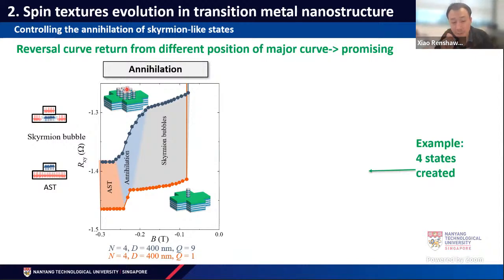small nanodots. However, when we did the measurements, we realized that the electrical measurement is actually quite sensitive to the upper layer nanodots. For example, if we only have 1 or 2 nanodots on top, and we change the diameter or the number of the nanodots, we can see differences in the AHE results. So that's a proof that we are able to see it. Of course, there's still a background from the bottom layer. On top of that, when we flip the magnetization of the top layer, the nanodot, the bottom layer remains the same.